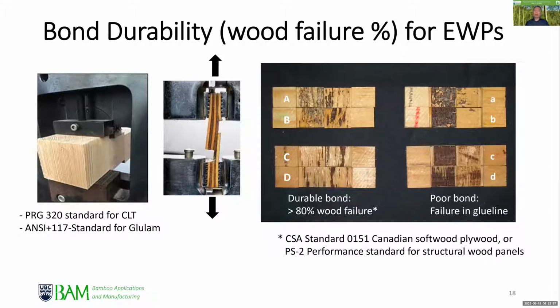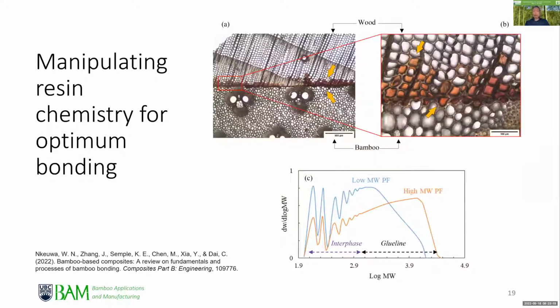We expected bamboo product to be a suspect that has to be looked at seriously to improve the failure percentage of bamboo fiber. And one of the strategies to deal with that is to manipulate the molecular weight distribution of resin, and even combining that with wood, it actually helps to improve the durability.